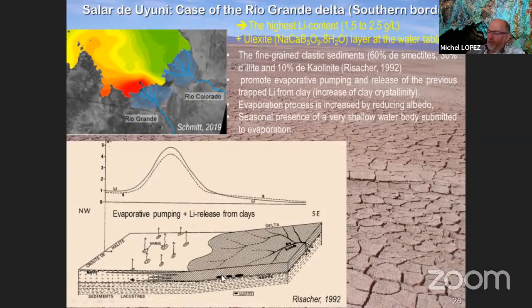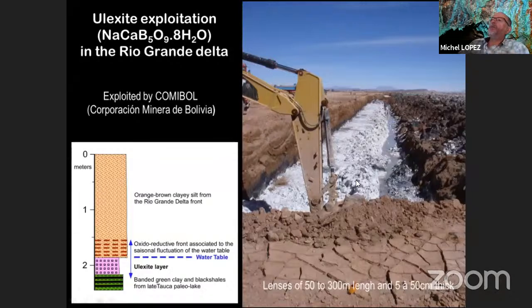And this ulexite deposit are or were exploited. I don't know now if they are still exploited, but these borates were exploited by the Comibol. You see here the borate layer. The clay was removed from the surface. This is more or less the water table position. Below is water. You see the water here. And the borate lenses that are 50 to 300 meters in length and 5 centimeters to 50 centimeters thick were exploited.